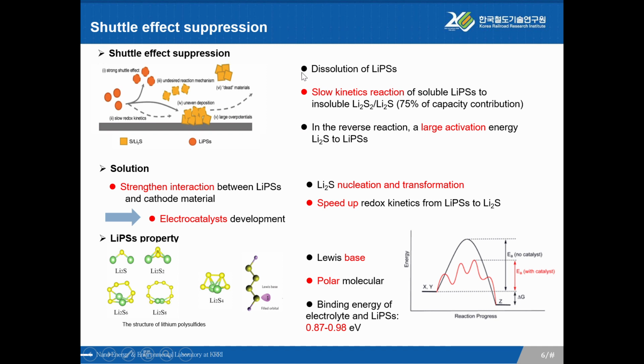Actually, shuttle effect is because of dissolution of lithium polysulfides and slow reaction kinetics of soluble lithium polysulfides to insoluble lithium sulfide. But this part can contribute 75% capacity. So it's very important. In the reverse reaction, there is a large activation energy from lithium sulfide to lithium polysulfide.